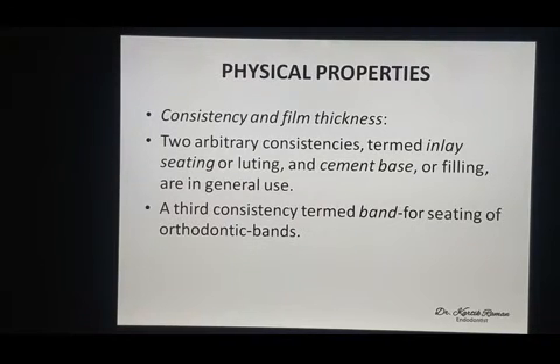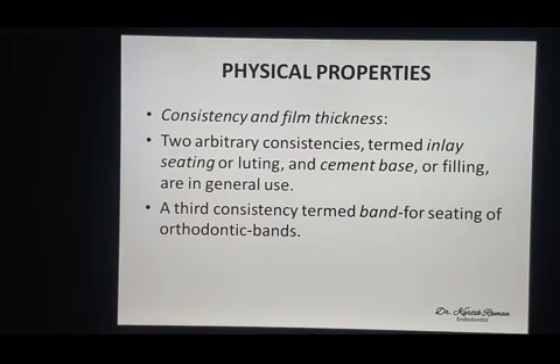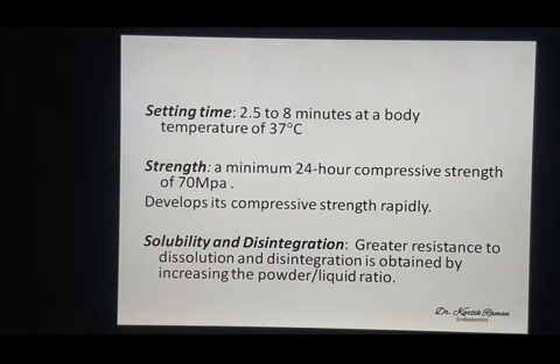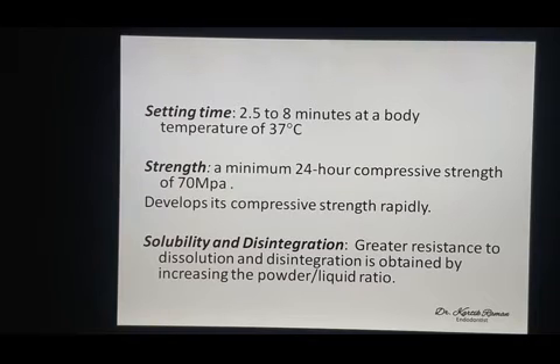The first consistency is called the luting consistency or inlay seating consistency, and the second one is the cement base or filling consistency. A third type of consistency is used for seating the orthodontic bands. Before the common use of glass ionomer cement, zinc phosphate was very commonly used for luting of the orthodontic brackets. Setting time is 2.5 to 8 minutes at body temperature. And strength: in 24 hours, it gains a minimum strength of 70 megapascals. And it has a great resistance to dissolution and disintegration.